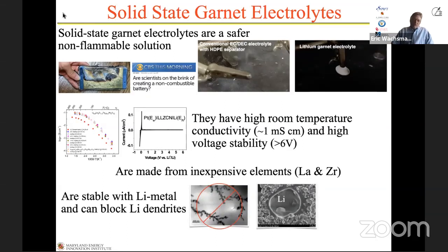But the aspect of this, which has made these quite attractive besides the safety, is the fact that they're stable to lithium metal. And the battery world is trying to get towards a lithium metal anode because basically that will increase the capacity of your anode on your battery by about a factor of 10 relative to conventional carbon-based anodes.